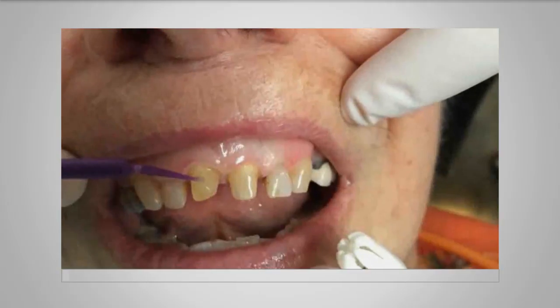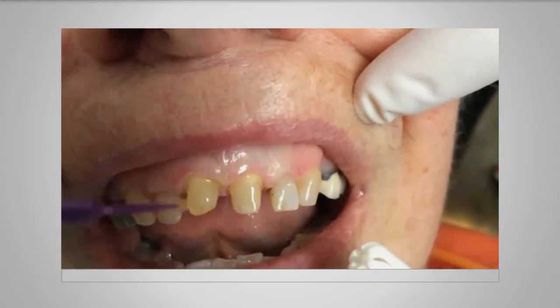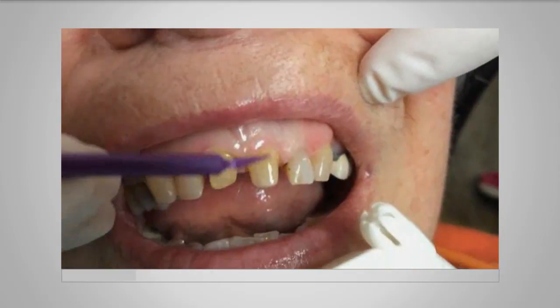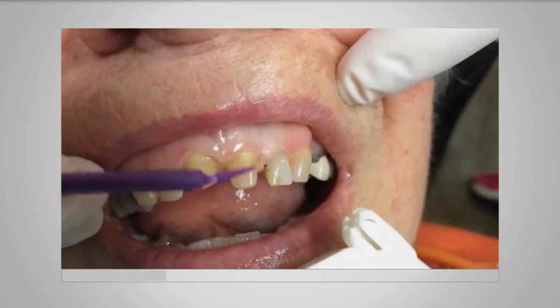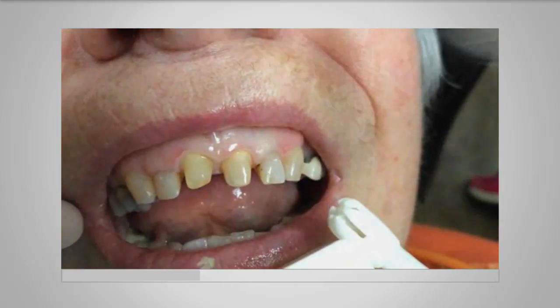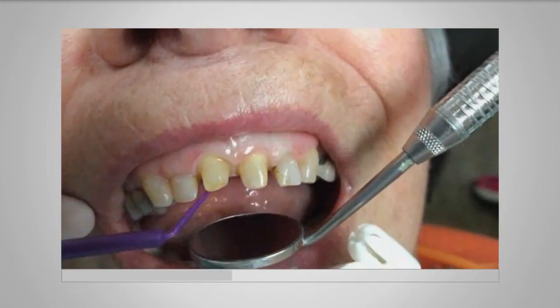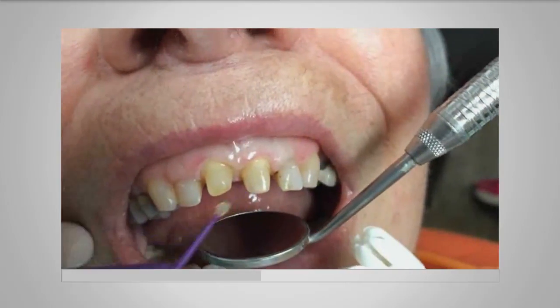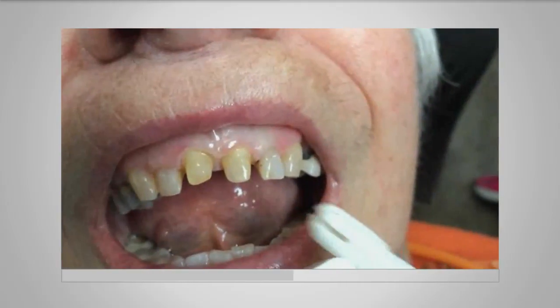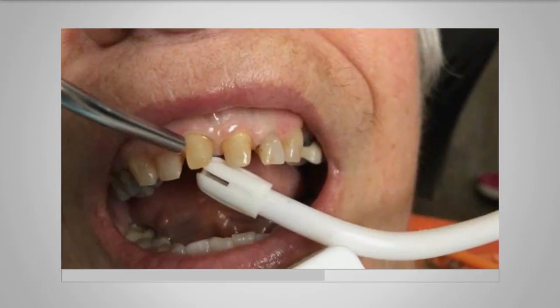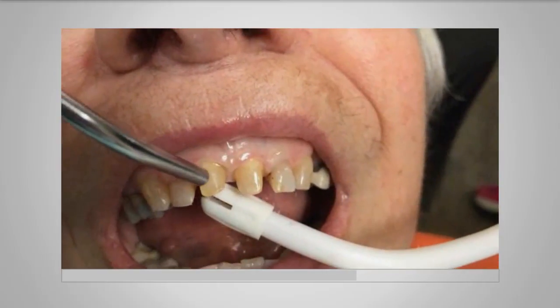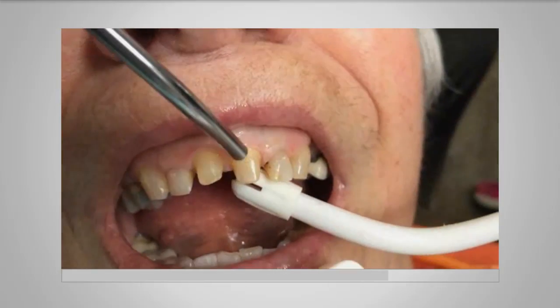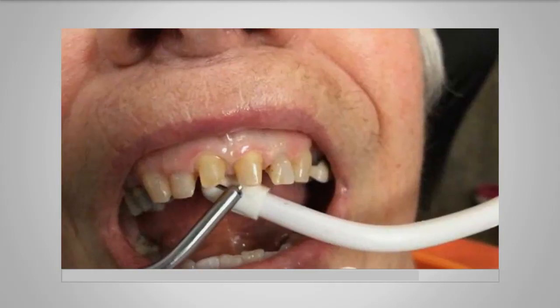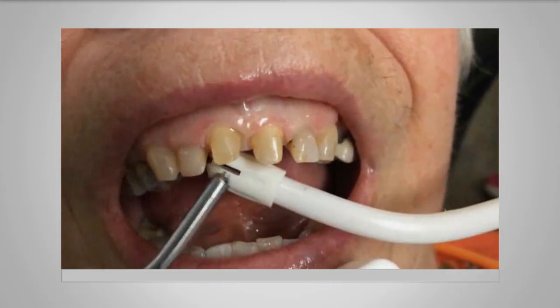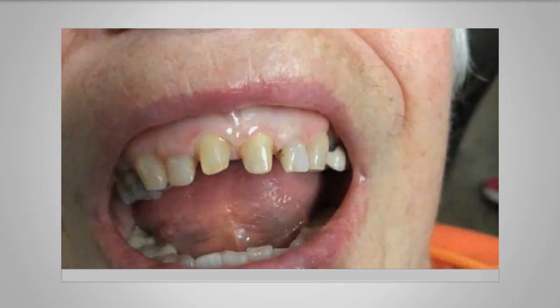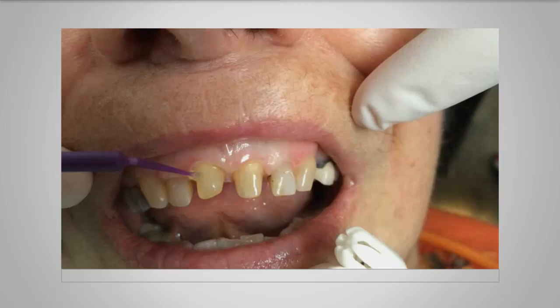So I just wanted to show you how I do it. So here I am using a self-etching adhesive. One of the important things here about self-etching adhesives is that you really got to scrub. That's how you get self-etching adhesives to really work. You scrub them. Now it's better if they are more acidic. You can get those to work better, but you got to scrub. And then another thing is that you got to blow them with air a good 5 seconds. Look how long I'm spending, because you want to get all the water, all the alcohol, acetone, all those carrying agents. You want to get those out. So you blow for a good 5 seconds.